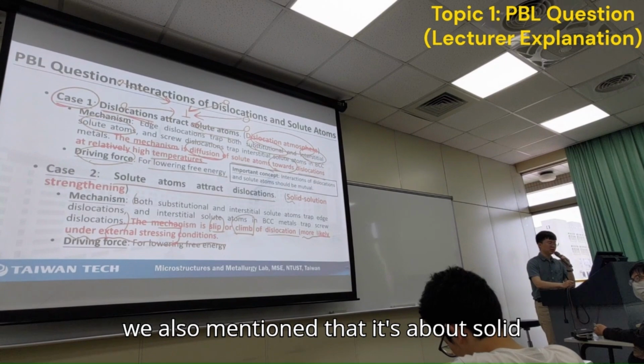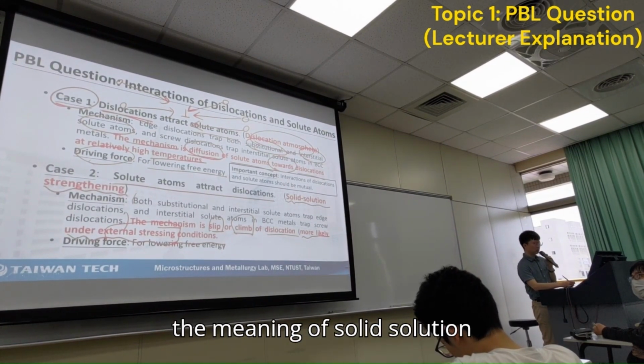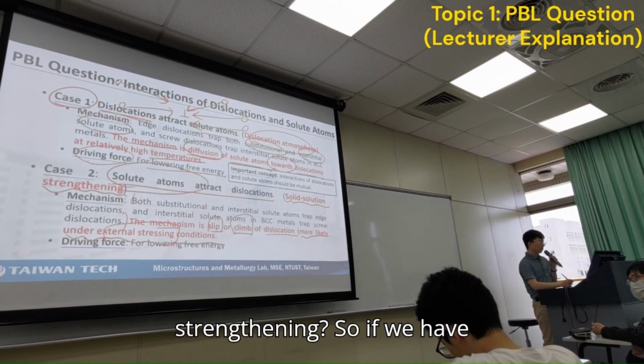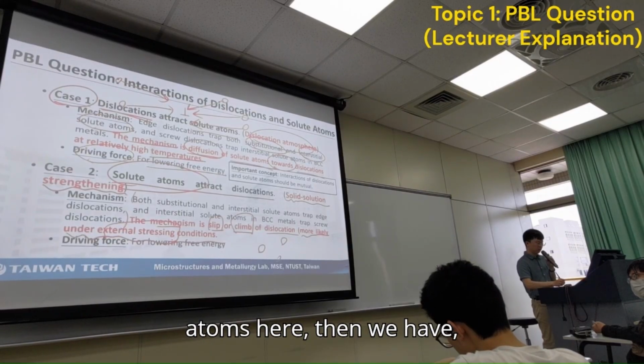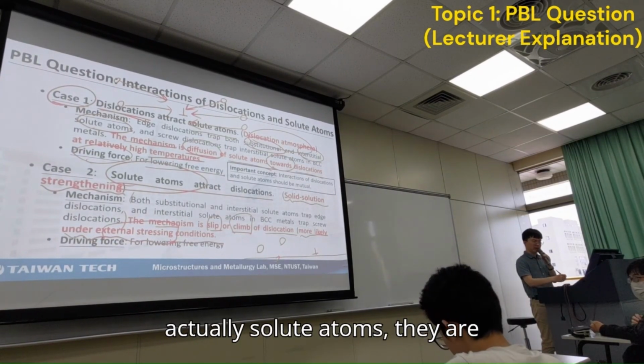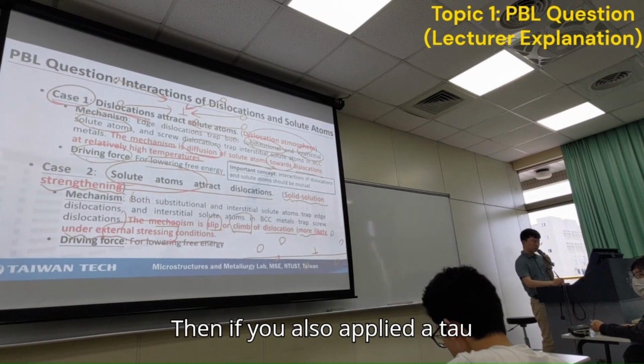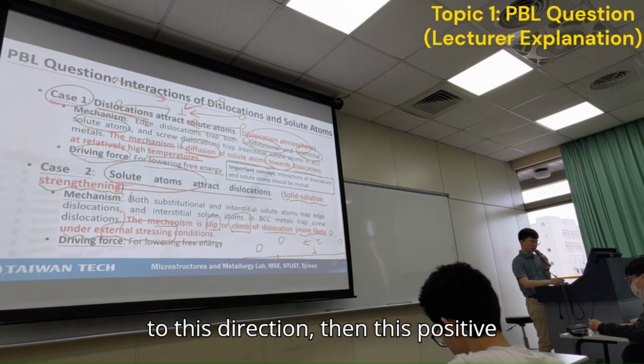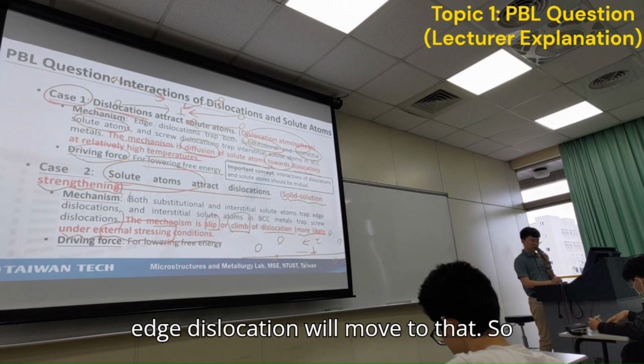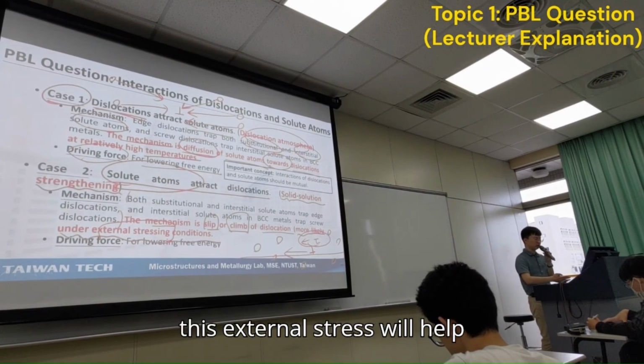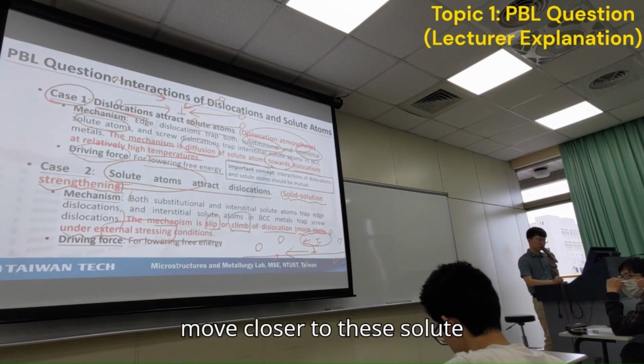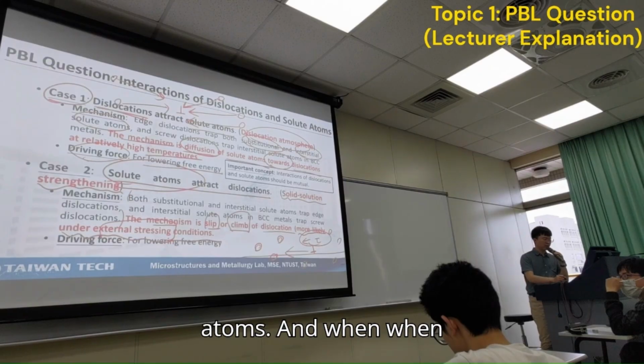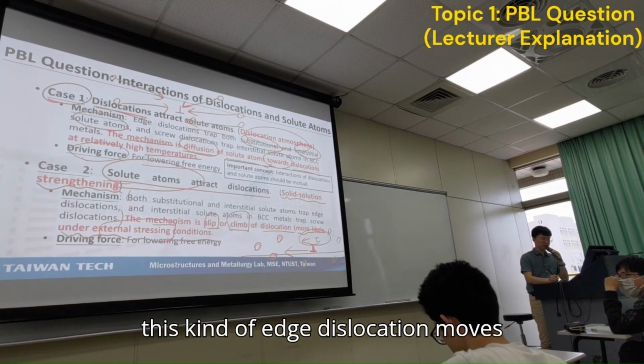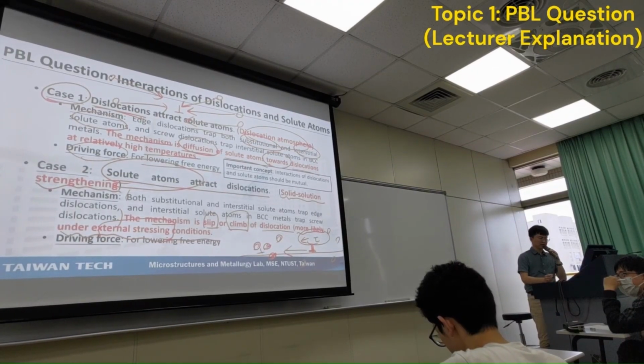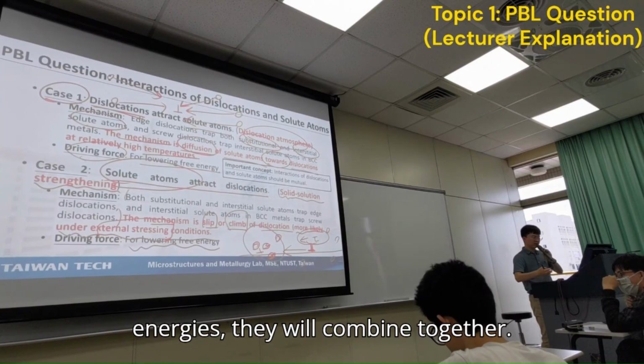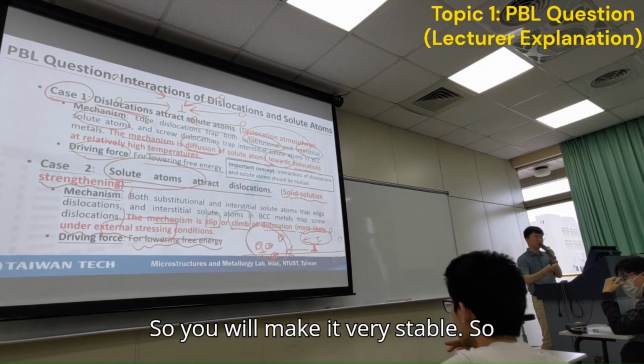We also mentioned solid solution strengthening, right? So what's the meaning of solid solution strengthening? If we have solute atoms, for example, we put solute atoms here. Actually, solute atoms are everywhere, so maybe here and here. Then if you also apply a stress in these directions, this positive edge dislocation will move to the left. So this external stress will help dislocation motion, making it easier to move closer to these solute atoms. And when this edge dislocation moves close to, for example, these few atoms, then in order to lower the free energy, they will combine together. So it will make it very stable.